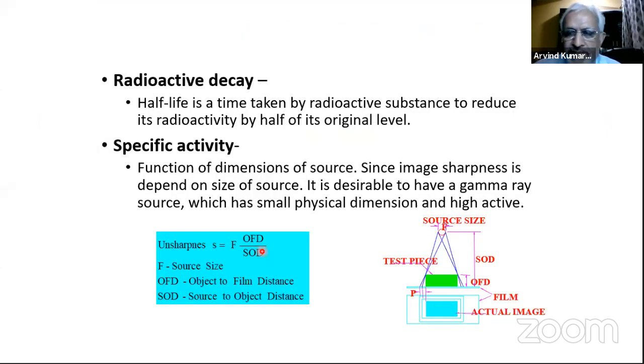So here the geometrical parameters are important: the distance of the source to the object and the distance of the film from the object. The film has to be as close to the object as possible, because we want to control the divergence of the radiation as much as possible. If I have a very long film like this, my radiation from here falls here, going towards the length of the film, where actually my thickness is only this much. If this much is appearing like such a long thing, that means I have very high divergence, and I will not be able to get a good image.